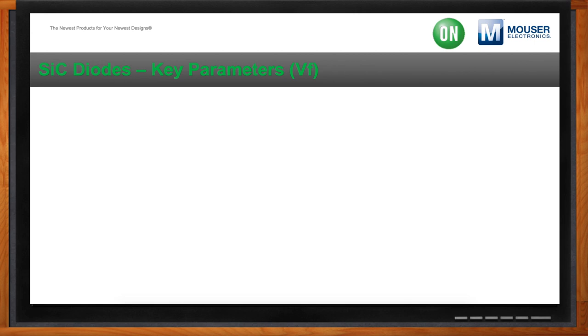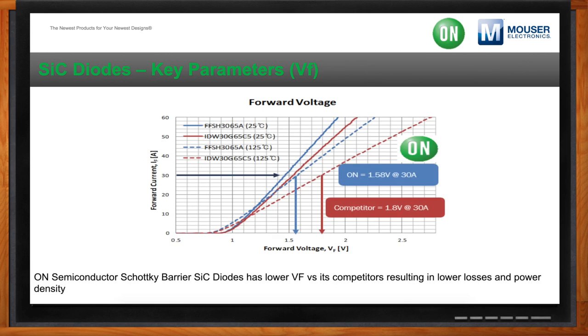And what that really does is that says, okay, when your device turns on, how quickly does it turn on? The quicker it turns on, the less leakage you have, and in turn, the less energy you're using. So onsemi uses a Schottky barrier SiC diode that has lower VF than what we can measure with our competitors. This results in lower losses and greater power density.